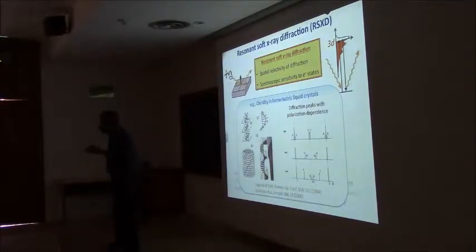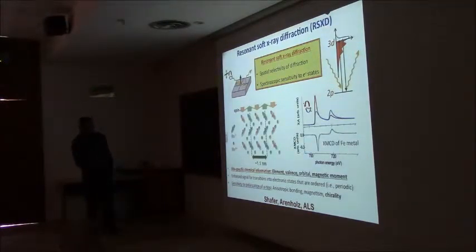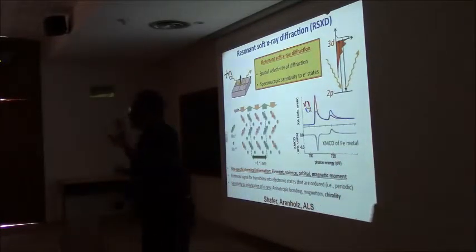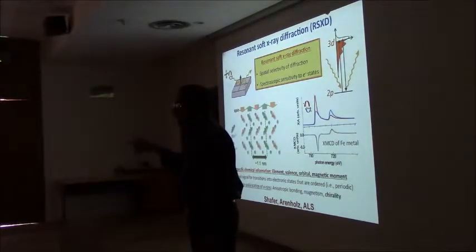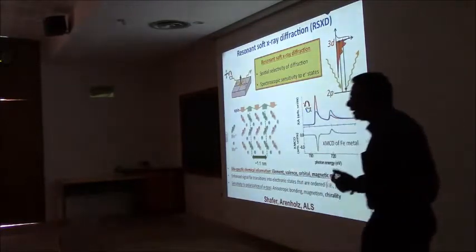There is no magnetic system here. So I'm so glad Ines brought up this. Typically, when you have circular dichroism, the M part is a very specific thing. If I have something that breaks time reversal symmetry, then it absorbs circularly polarized light differently, left and right. That's this data. And the question is, what other sources can give rise to circular dichroism? One of them is a handed behavior, and you can think of it exactly the way that Ines was talking about. That there is a curl of the P that acts like a virtual magnetism.